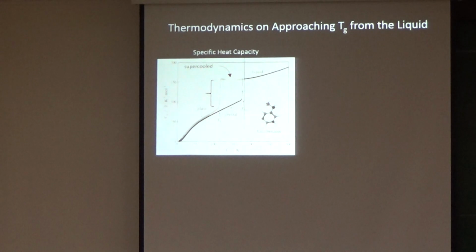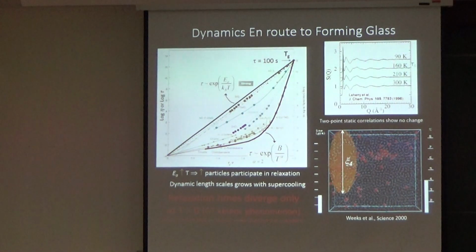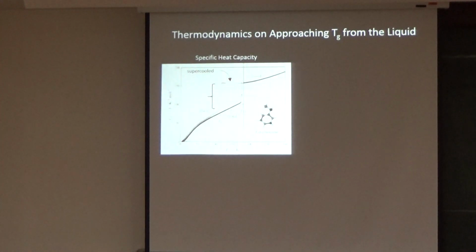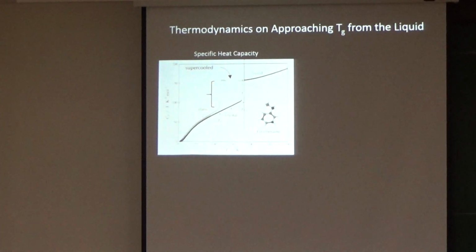Yes, so this is the liquid branch. I'm sorry about this, I think I'm pressing more than one. It goes into glass at this point. Yes, in principle it could have also gone to a crystal, but across this entire curve, you're maintaining cooling rates so large that you never let the crystal form. You never let the nucleus form. Because once you form the nucleus, it's immediately a first order transition that's going to go to the crystal state.